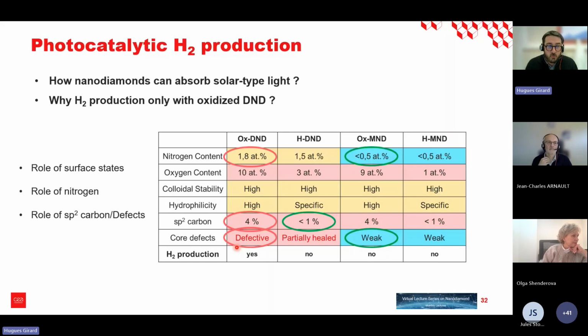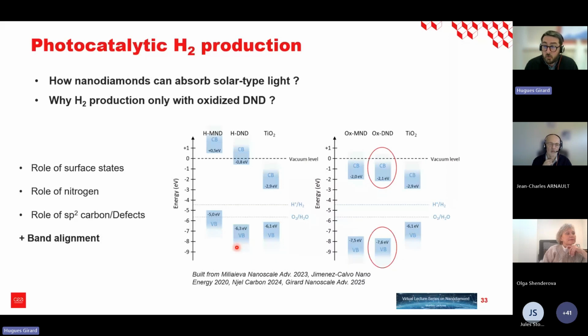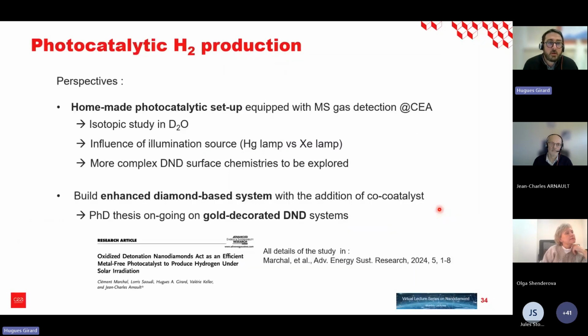But another thing to take care of is the band alignment, because as for any kind of semiconductor, you also need to have a good position of the conduction and valence band if you want to make some hydrogen from the protons, and also if you want to oxidize the water, which will give you some protons also. And you can see here that the alignment for the oxidized detonation nanodiamonds is favorable for these two kinds of reaction.